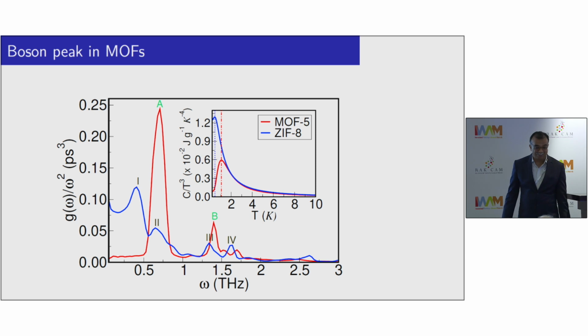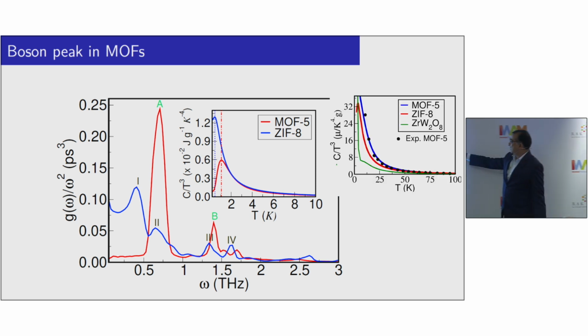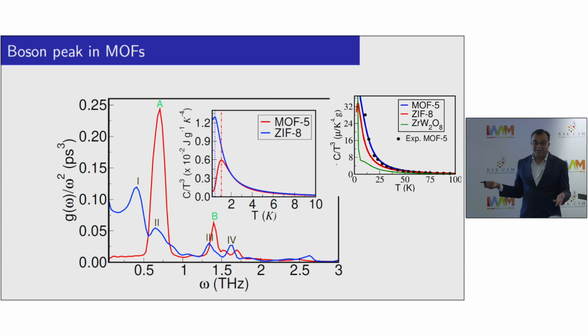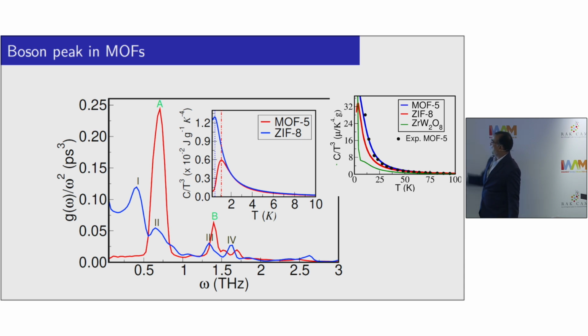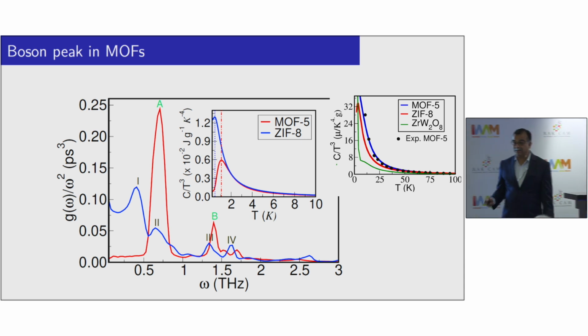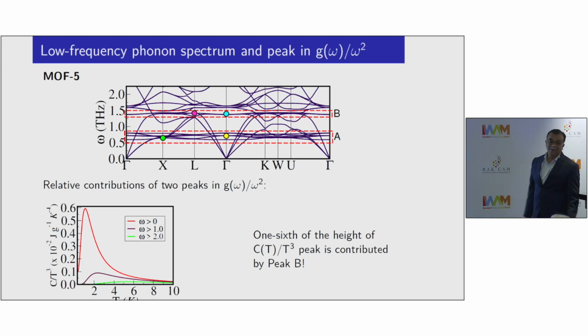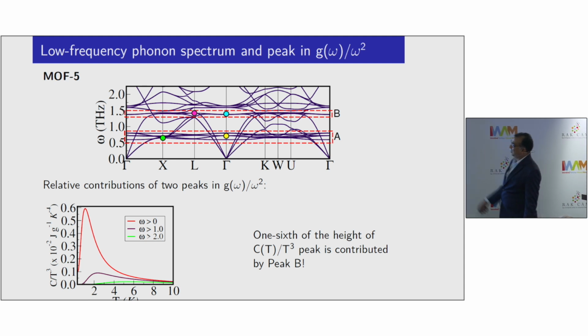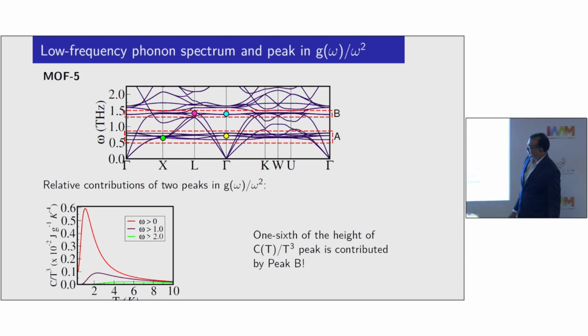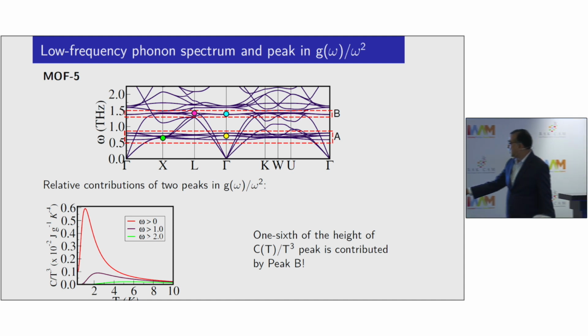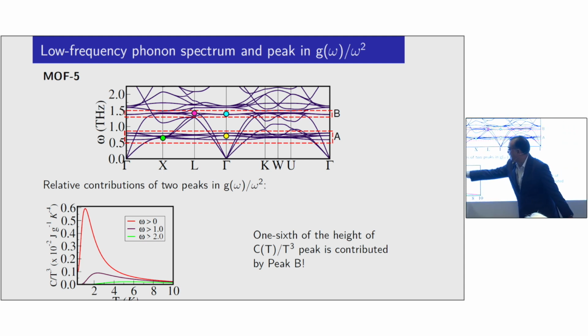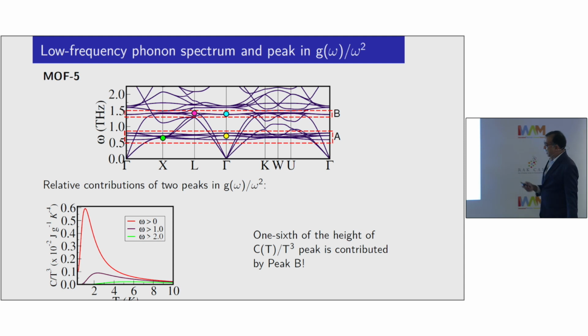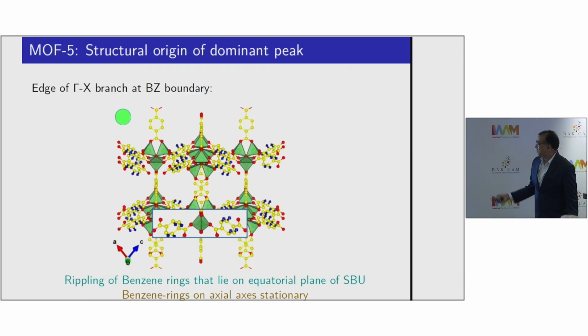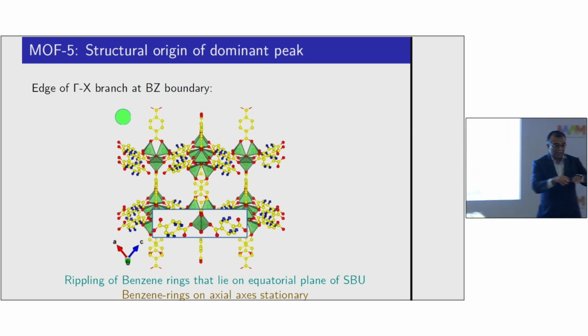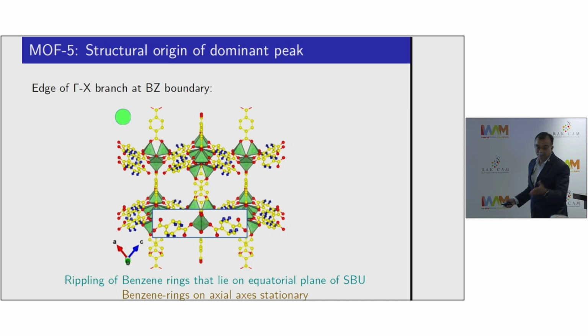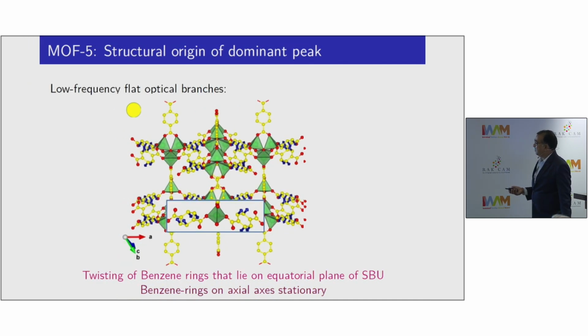I guess not so unexpected of MOFs. And indeed, if you see the experimental data here, this is what we said. It was a prediction we had, but luckily experiments already existed, and we could verify our prediction for MOF5 particularly. It satisfies what we have predicted from theory. So what is responsible for these boson peaks in MOFs? And that's where we look at the mode-by-mode contribution to the excess specific heat. And what we find is in MOF5, most of the excess specific heat is caused by basically these two sets of phonons, which are grouped in A and B. And that is the phonon which involves displacements, again, of the linker molecule, translational motion, which gives rise to librational-type shear distortions. And this is the set B.